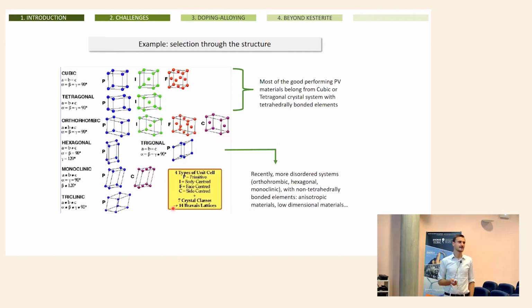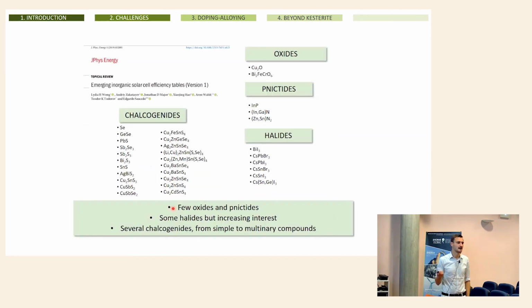Okay, in terms of organic or hybrid solar cells, I'm not an expert, it is not my field of expertise. I think that hybrid perovskites are beautiful materials demonstrating extremely high efficiencies, really very nice. The main problem is still the durability of the material, so they are unstable materials. And you know, for a photovoltaic material, you need to demonstrate 30 years duration under operation. And perovskites are extremely far from that. So even if efficiencies are very nice, they have to demonstrate that they can withstand 30 years of operation, like silicon, like CZTS, or like telluride that have demonstrated so far more. Yeah, thank you very much.